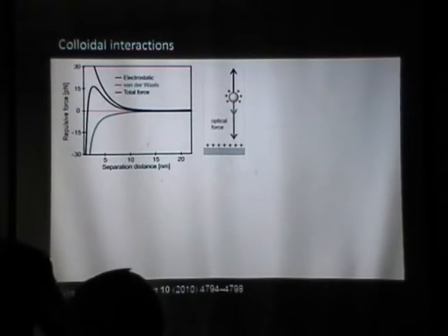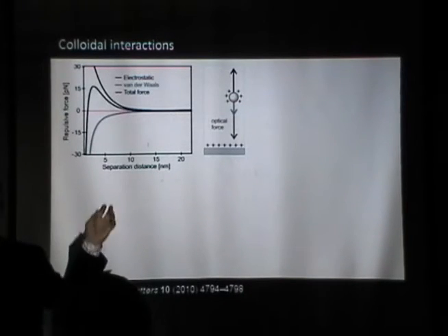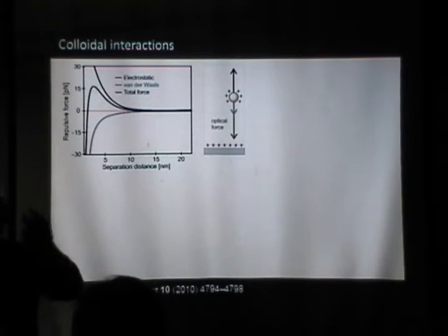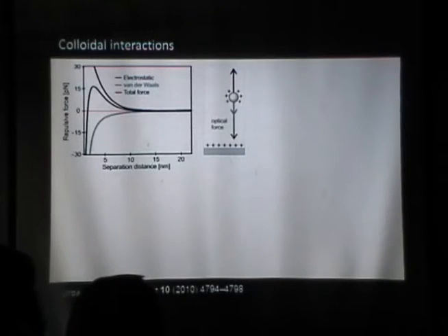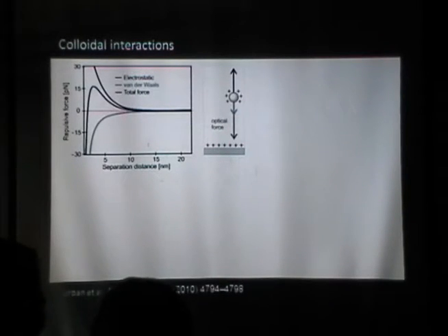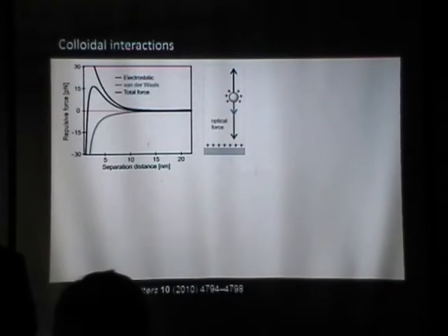So what's the idea? Most of these nanoparticles are made in suspension, so they are colloidal nanoparticles. That means they are stabilized in solution by electrical charges. So you have nanoparticles with some charge at the surface, and by electrostatic repulsion they remain stable in suspension, right? Now, if you place a substrate with the same charge as the nanoparticles, then you will have a similar colloidal interaction. The nanoparticles will not go to the substrate, they keep distance due to an electrostatic barrier.